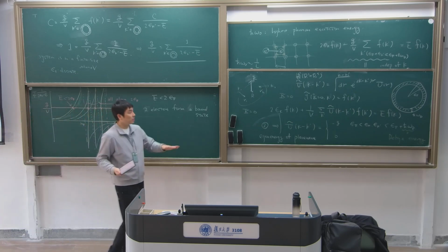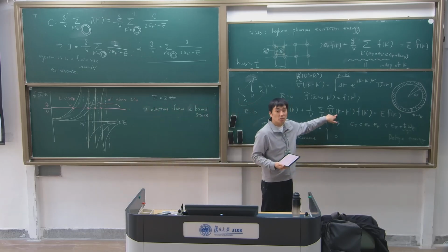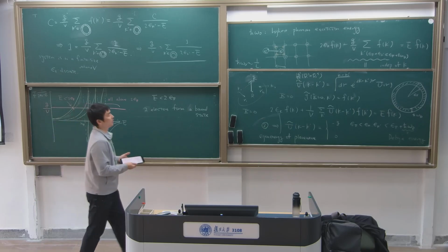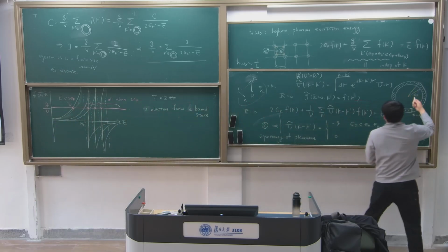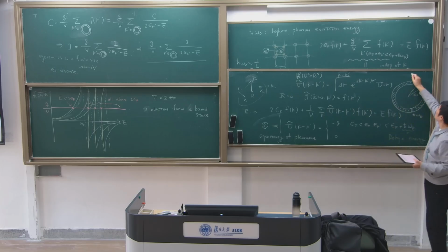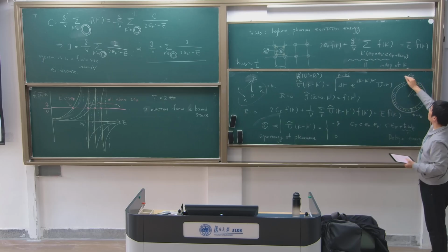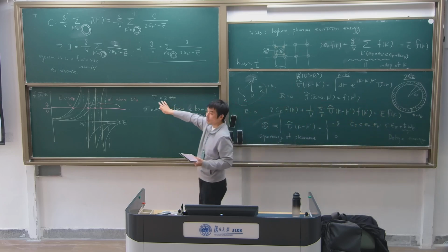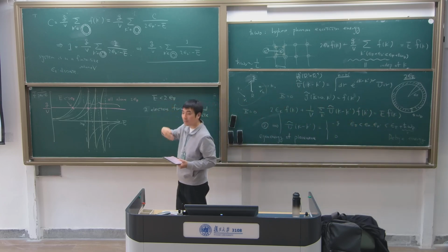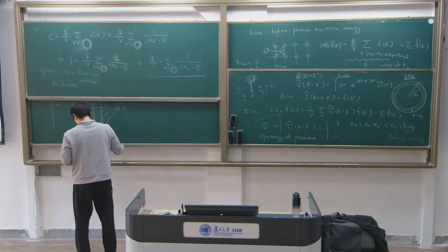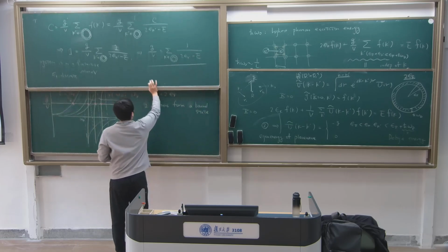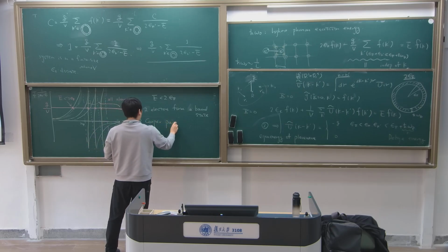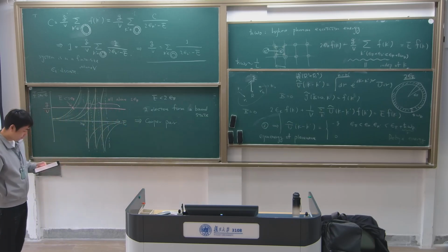But if there is no interaction U, the 2 electrons can have energy. If you consider the k inside of this equation, the lowest energy is epsilon F, the Fermi energy, and if there are 2 electrons, the lowest energy is 2 times the Fermi energy. But the energy now is less than that, which means that it forms a bound state. So this is called the Cooper bound state. It's a very simple calculation, but it's very useful.